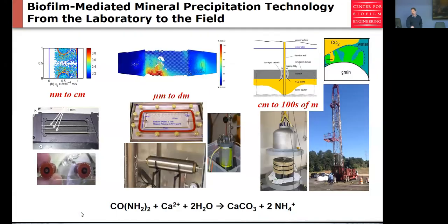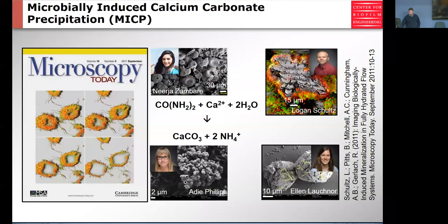So we're trying to understand how calcium carbonate grows in the pore space, basically. So we've done this on the microscale, and you've already seen these capillaries. This is kind of a porous media micromodel, all the way out to the field scale. And we've now been out 6 times and have done this successfully. It turns out that really these macro scale outcomes that we have, like plugging a leakage pathway, are based on microscale processes. So to understand the microscale processes is really important in order to develop better approaches on the macro scale, right? On a commercial scale, for instance. So I want to focus on the micro scale.